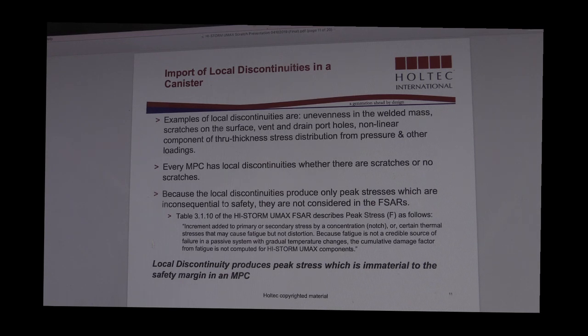The reason that peak stresses are not of significance as it relates to the MPC is that by code definition, peak stresses are only objectionable from a standpoint of fatigue or brittle fracture. So in the context of the MPC, it is a passive system. There's no moving parts, there's no active cooling system. When the MPC is in long-term storage, it's in a static resting state. There are very, very minimal pressure and temperature fluctuations. So there's no credible risk of fatigue for the MPC canister.